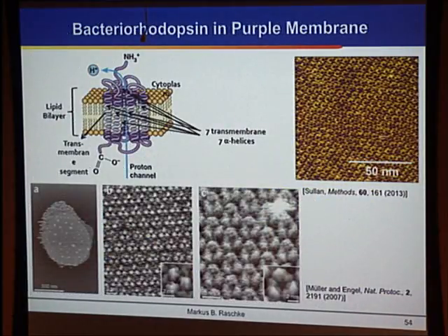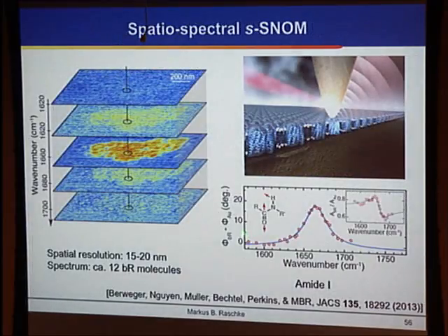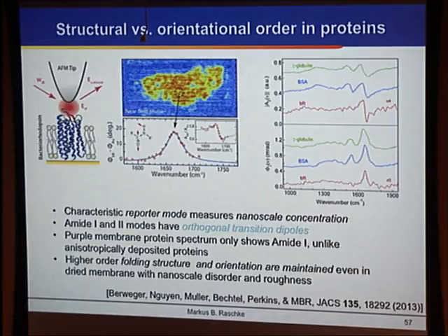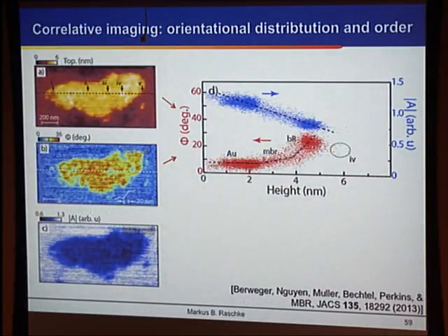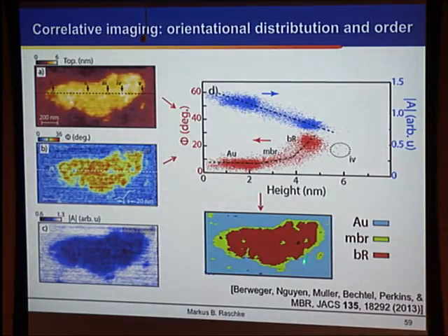We can do this in proteins, whether we look at transmembrane proteins, which have a preferred orientation normal to the membrane, and we can image this. Again, we can do spectroscopy on these on the amide mode, looking at this transmembrane protein distribution, and from that we can actually learn from the spectral response, where we only see what's called the amide 1 mode, that with these two modes in the protein being orthogonal, in these membrane layers the molecules are actually oriented in this fashion. We can then look at disorder and distribution of those, and then get corresponding spatial distributions and defects in these membranes.